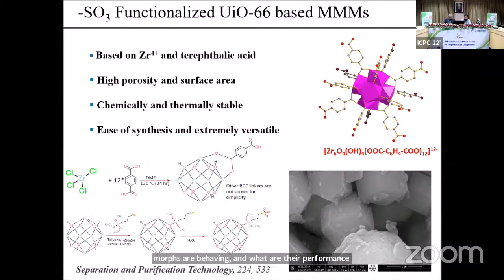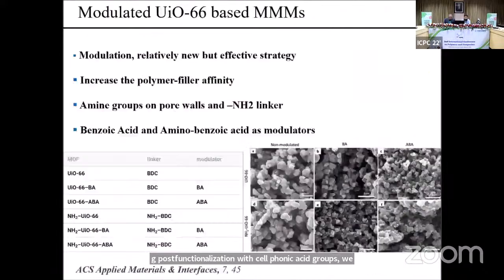In one of the studies, we used a zirconium based metal organic framework, which is also called UIO66. This metal organic framework shows very high porosity and very high surface areas. It's very stable both thermally and chemically. However, what we did in this study, we functionalized it with sulfonic acid groups with the objective to induce CO2-philic groups. So we wanted to improve the properties of this very well studied, very well known MOF, UIO66, by using post functionalization with sulfonic acid groups. We were able to produce very well defined porous MOFs.